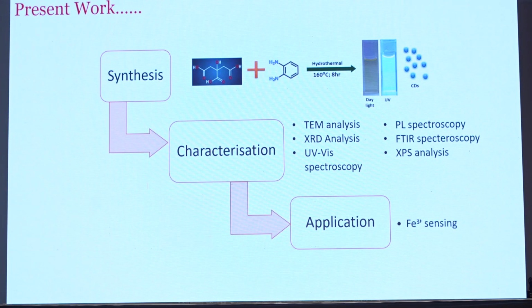Moving on to the present work. It involves the synthesis of carbon dot from citric acid as carbon source and orthophenylenediamine as nitrogen dopant under hydrothermal condition at 160 degrees Celsius for 8 hours, and we obtain a blue luminescent carbon dot.